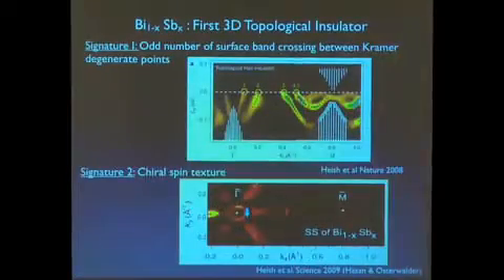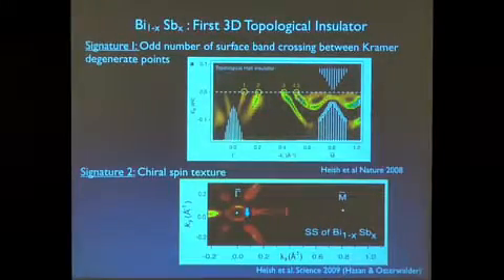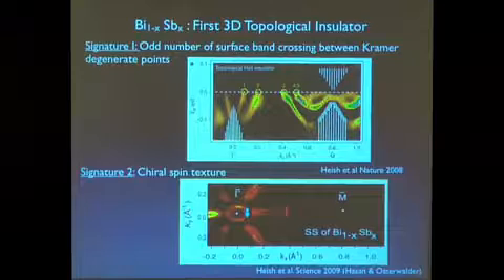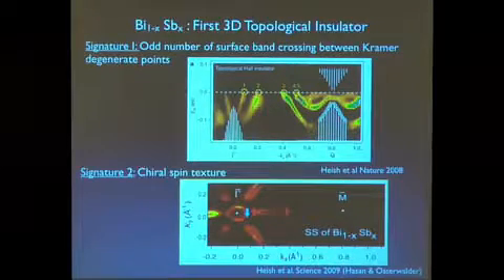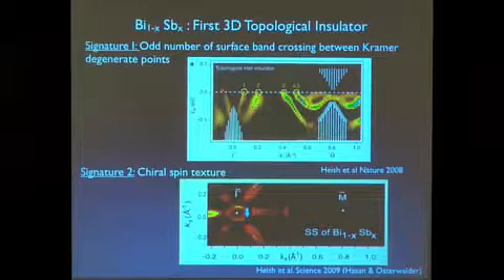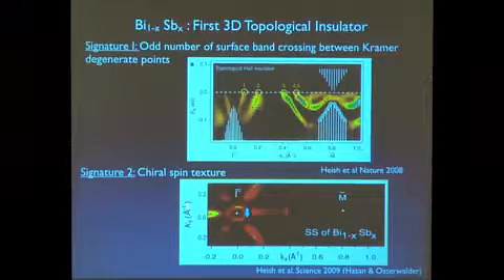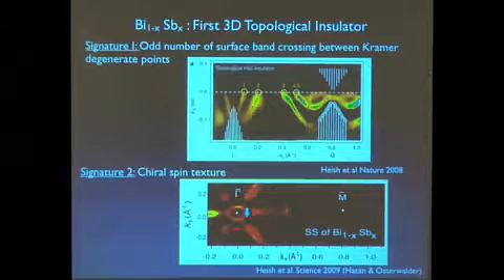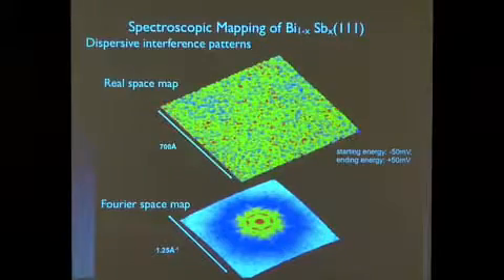And my colleague Zahid Hasan used photoemission spectroscopy to look at how electrons move on the surface of this compound, and basically looking for the two signatures, one of them having to do with the odd number of crossing of the chemical potential crossing the bands of the surface electron, and the other one having to do with the spin basically being textured, of the electron spin and momentum looking like they are locked at least in the center of the zone. So we set out to look at this compound.